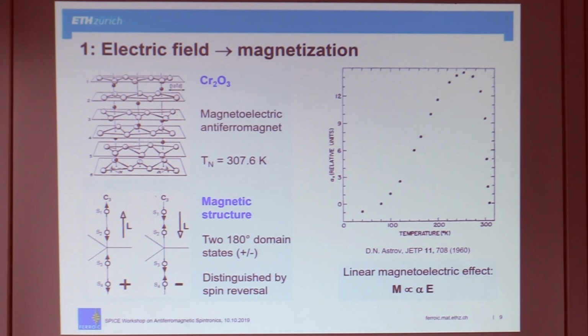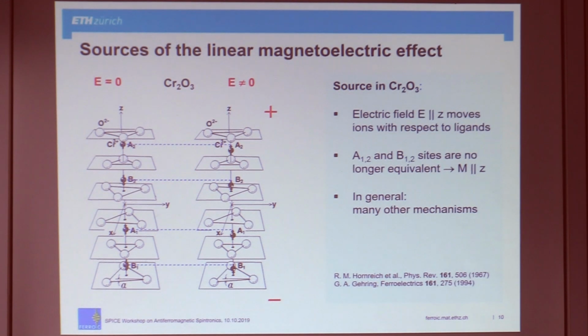So it's not very difficult to understand the origin of this effect. For chromium oxide, you can look at it like this. Here is the chain of up-down spins again. Each chromium ion sits in this distorted octahedral cage. Here you see the octahedron a bit better. You have this quadratic plate, and then the apical oxygen ions around this empty cage. The same here, but it's a bit distorted. You have a larger triangle and a smaller triangle, and the larger one is a bit rotated. The chromium ion is always a bit closer to the large triangle. Here, there, here, and there. And also the spin of the chromium ion. In this domain state, it's always pointing towards the large triangle. So it's pointing towards this one, that one, this one, and that one.